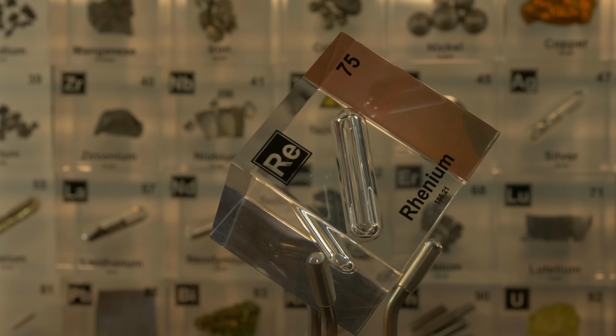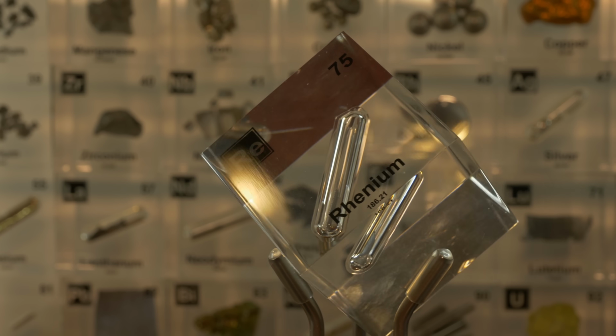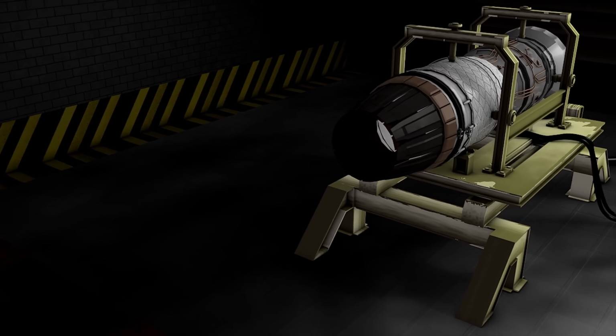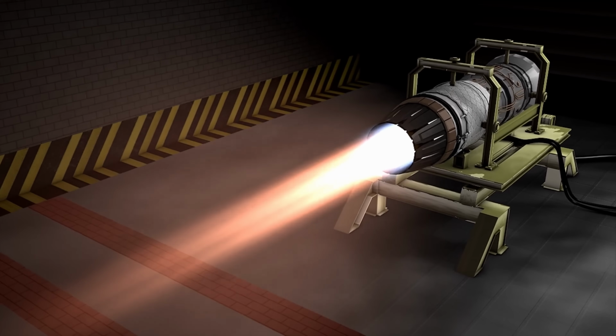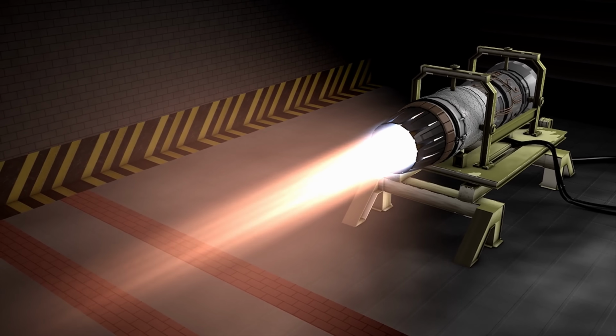Now, these alloys also maintain excellent strength at high temperatures. One important use of tungsten-rhenium alloy is in thermocouples, devices that measure temperature. A specific thermocouple type is made from a wire of tungsten with 5% rhenium paired with a wire of tungsten with 26% rhenium. This combination, called Type C thermocouple, can measure extremely high temperatures up to 2200 degrees Celsius, far beyond what platinum thermocouples can handle. Such thermocouples are used in jet engine development, rocket engines, and scientific furnaces, anywhere you need to measure very high temperatures accurately.